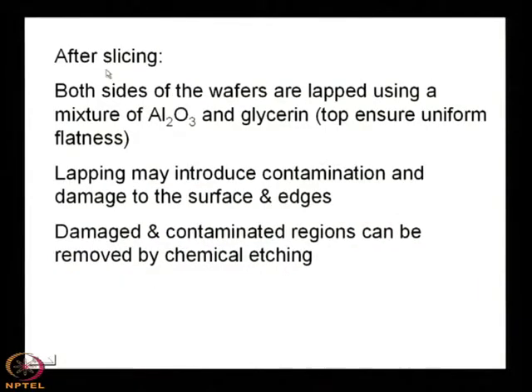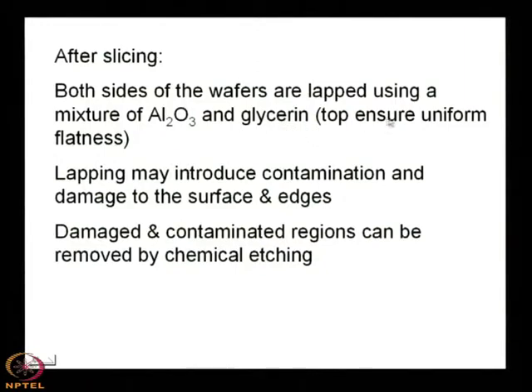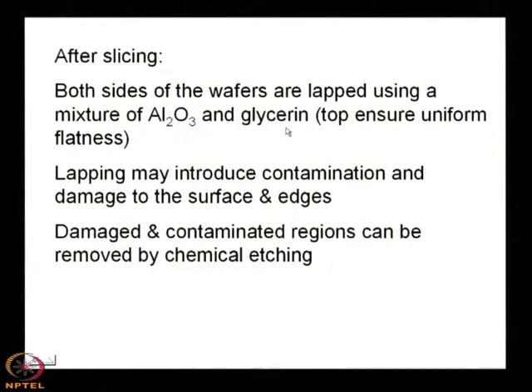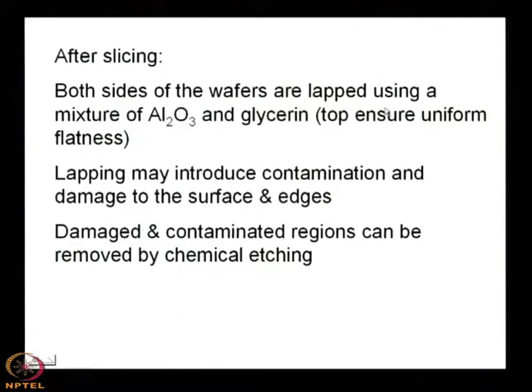After slicing, both sides of the wafers are lapped using a mixture of Al₂O₃ and glycerin to ensure uniform flatness. Lapping is essentially rubbing — using a cloth pad with alumina and glycerin — now performed with a crystal lapping and polishing machine, which ensures surface uniformity.